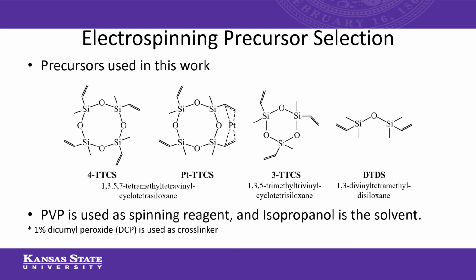PVP is used as a spinning reagent, and isopropanol is the solvent for PVP. And then 1% DCP was used as a cross-linker for 4 TTCS, 3 TTCS, and DTDS. But the platinum TTCS is a complex of platinum and 4 TTCS, so platinum will work as the cross-linker itself.